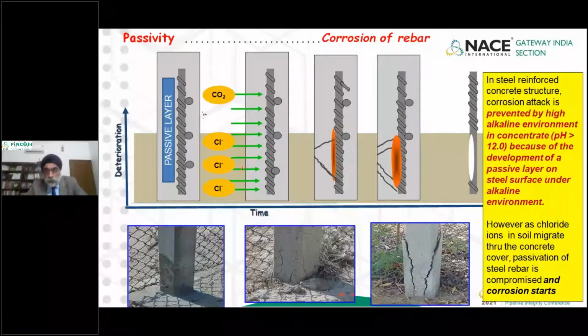Both these basically damage the passive film and start the process of corrosion. Chloride ions obviously start the corrosion process much faster as compared to the carbon dioxide impregnating through the concrete in the atmospheric zone. So when the chloride ions impregnate, they form rust. The rust, as I said, is 6 times the volume of an Fe ion. That pushes the concrete and starts the formation of cracks. Now this becomes a repetitive cycle, causing the concrete to crack and then eventually fall down.